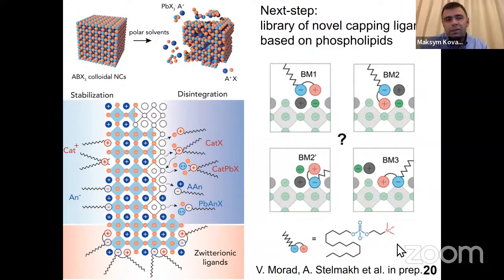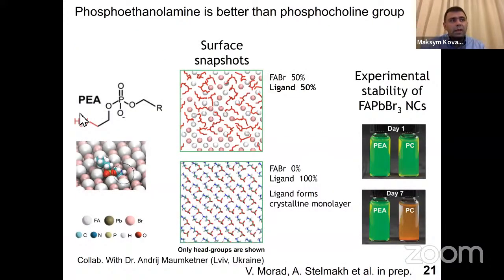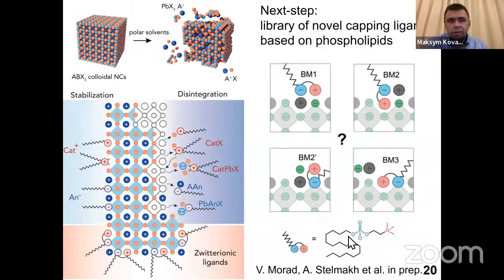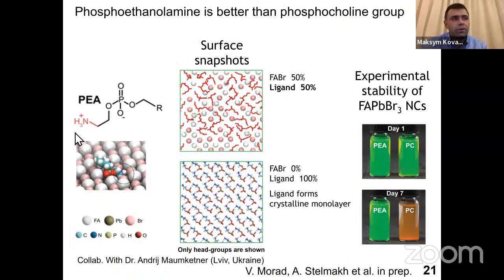Because in principle, this is a permanently charged cation, and it sounds like it's a good group, but it's a little bit bulky for this site. And so we then checked, what if we take a primary ammonium group, which is three hydrogens instead of three methyl groups? The one which is primary ammonium, we call it PEA, is phosphoethanolamine. So this group is phosphoethanolamine. And just for the sake of language, this is phosphocholine, and this is phosphoethanolamine.